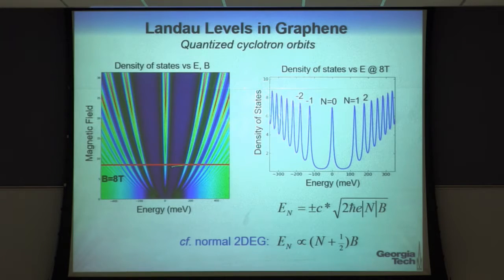Okay. If I take a cut through that, I see a density of states picture that looks like this, and the significant thing about graphene is that it has a peak at 0 energy, and that does not disperse with magnetic field. That's a consequence of the topology of the graphene band structure itself.